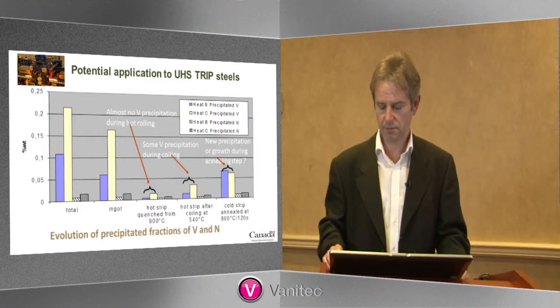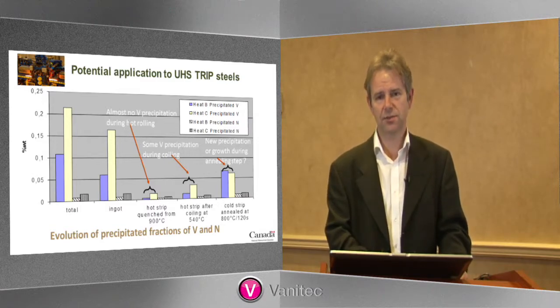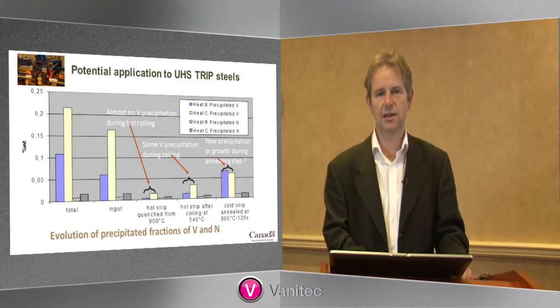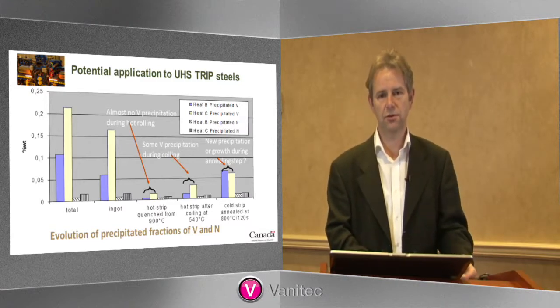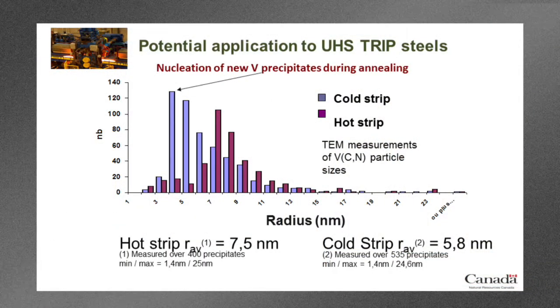This I'll explain in a minute. Question is, this extra precipitation here measured by this dissolution technique, is it due to new precipitates formed after cold rolling, or is it due to growth during the annealing step? Here we have TEM data showing the size distribution of the vanadium carbonitride precipitates at 2 points. The red bars in this histogram were taken from the hot strip, and the blue bars were from the cold strip. What you can see is that the mean radius of the hot strip precipitates is about 7.5 nanometers as measured in the TEM. Whereas in the cold strip, the blue histogram, we have a decrease in that mean radius, and it actually drops down to about 5.8 nanometers.